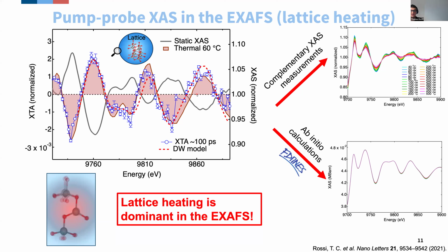So this delivers to us by how much the Debye-Waller factor increases when the lattice gets hot. So overall, the physics is not super interesting, right? It's a lot of lattice heating on these timescales, 100 picoseconds. But although it doesn't look very interesting, it turns out to be absolutely crucial for the interpretation of the data.